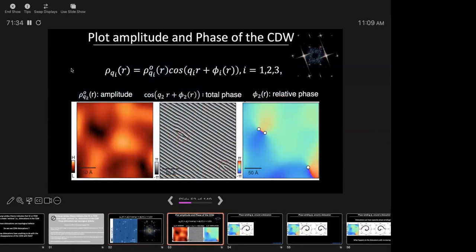So here's some region of topography, which I don't show here. This is the Fourier transform. Here's the extracted amplitude. Here's the cosine, this term, the phase, right? Total phase. And here, what I'm plotting is just this relative phase. What this relative phase captures is if you have a phase shift in the charge density wave at some given location, then you would have an extra relative phase that would be position dependent. Okay, does this make sense to everyone?